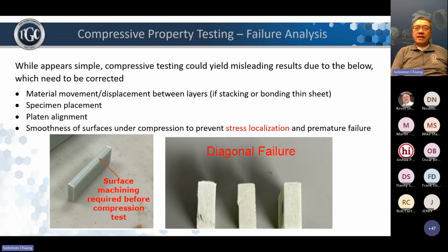On the left-hand side, it shows a protruded parting line. With protrusion, that's always the top and bottom die, and in between is your parting line. Before you test it that way, you have to sand off the parting line so that you don't localize all your stress on the parting line, and that gives you premature failure. Those results don't count.